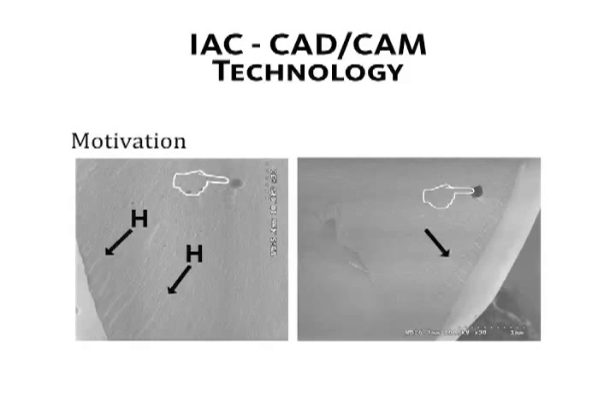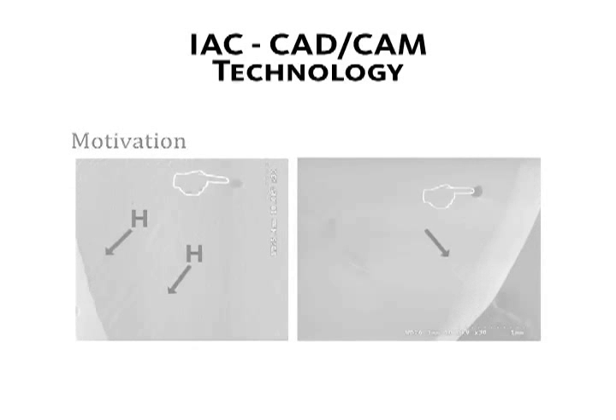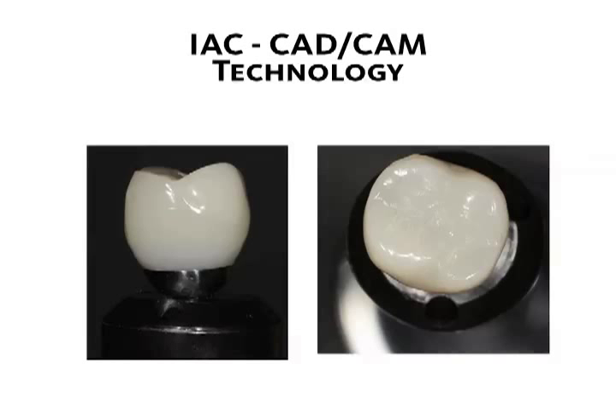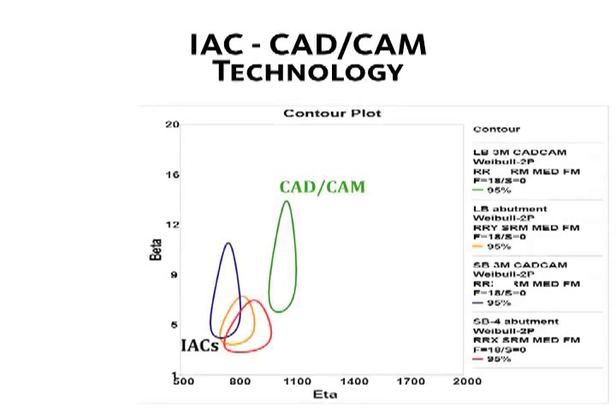An interesting aspect that we observed in our fractographic analysis was that voids were incorporated from packing with indirect composite. This motivated us to further test IACs made from CAD-CAM composites. This is the finished CAD-CAM IAC molar crown, and the results showed an improved mechanical performance of CAD-CAM produced composites compared to indirect composites used as IACs.